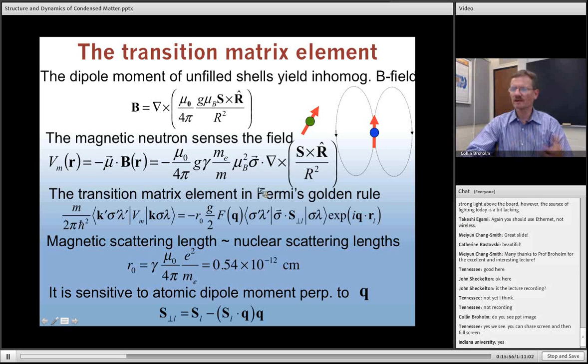So if you will, a result of the particular form of the dipole-dipole interaction will actually cancel out that particular aspect of the cross section. And this actually turns out to be some form of a blessing, or it's actually quite convenient in a sense that it's possible to get some information about the orientation of magnetic dipole moments in materials by looking at this so-called polarization factor.